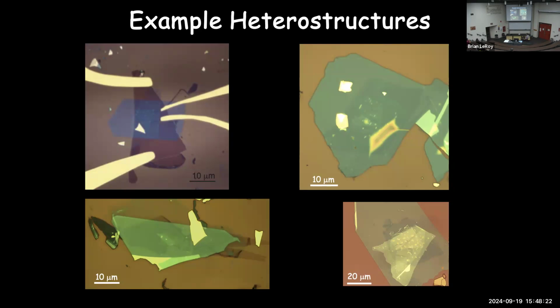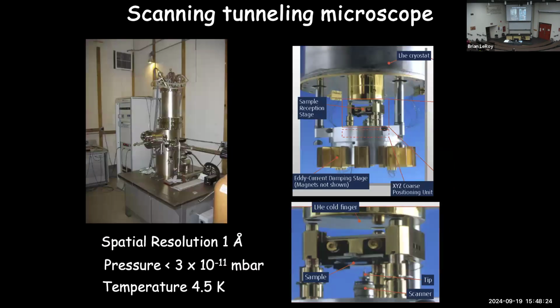And the way we're going to study these materials is with scanning tunneling microscopy. This is one of the scanning tunneling microscopes in my lab here. It operates at ultra-high vacuum so that we keep very clean surfaces. When we've made these samples, we need them to be basically completely clean on their surface so that we can come in with our little STM tip here and probe the behavior by bringing the tip very close